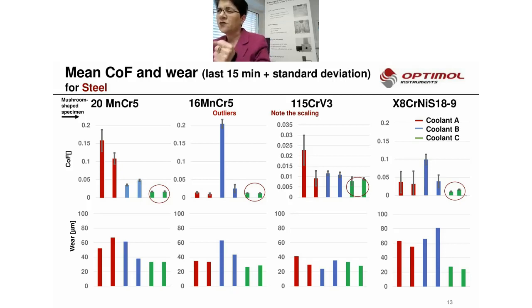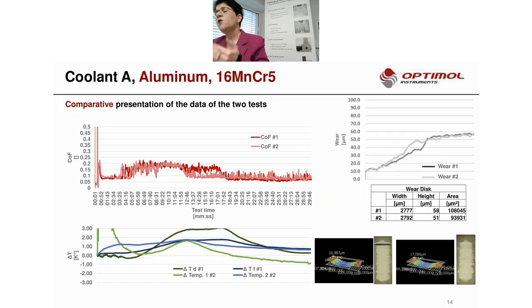Only in one case, we had one outlier, and the operator should make this test a third time. And you see that in all combinations, coolant C has the lowest value of coefficient of friction, followed, of course, by the wear values. And now we change from steel to aluminum, which is very important and interesting.